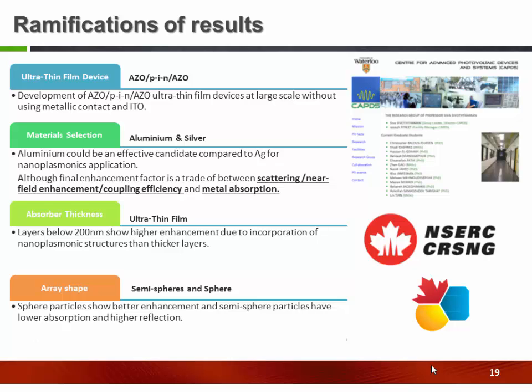Also, we have understood that ultra-thin is the best choice if you want to incorporate this type of nanoplasmonic structure, because the performance enhancement is better realized for this type of material. The other thing is the semi-sphere and sphere. Semi-sphere is much easier to fabricate because some sort of nano-island formation happens in the particle structure film. But the sphere also shows us the highest improvement. So both can be future research for our devices that will be followed in our group.